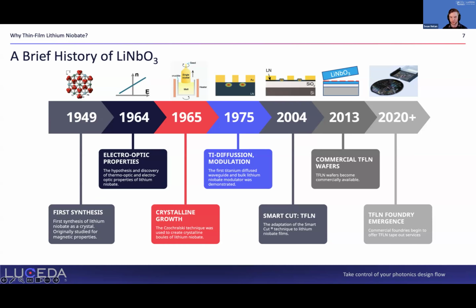After that, you want to make your devices smaller, faster. And with the onset of the smart cut process, which I'll cover again in just a second here, we were able to make thin films of lithium niobate. So what do I mean by thin films? Generally, the bulk lithium niobate films are on the order of 500 microns to 1,000 microns thick, whereas these thin films of lithium niobate are on the order of 100 nanometers to 1,000 nanometers thick. But this was still a very difficult process to achieve. So 2013, we really started to see these commercial wafers coming into play where you could buy a thin film of lithium niobate on a wafer that you could use. Soon after that, foundries started using them. So now we see the emergence of TFLN in the commercial foundries. So now you can order a wafer with devices on it with a PDK component set to implement in your system.